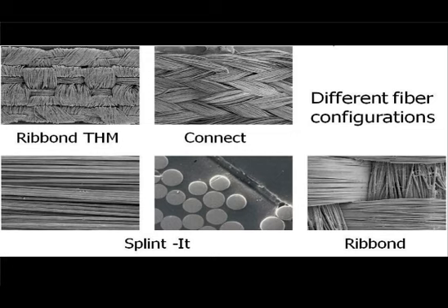The Splint-It material, which is a glass fiber material, either as a unidirectional glass or as a woven braided fiber. From the research that's been done, the lock-stitch weave tends to hold the composite at better flexural strengths, flexural modulus, as also it's more easily manageable, easier to place.